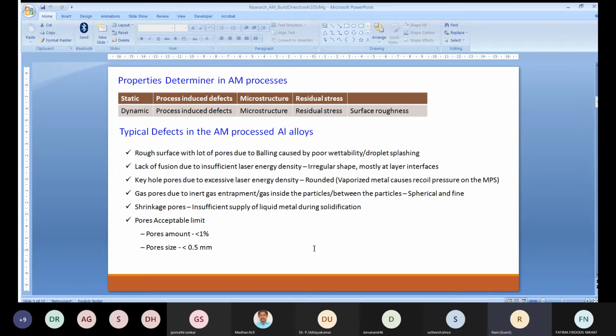Then comes shrinkage porosity. That is due to solidification. If you have a long, wide solidification range, insufficient supply of metal to the interdendritic region during solidification causes shrinkage porosities. We did a vast literature review and understood that if the porosity amount is less than 1% and those porosities are less than 0.5 mm, then these porosities don't affect the mechanical properties. That is the understanding we got. So this point is very important for industry people.